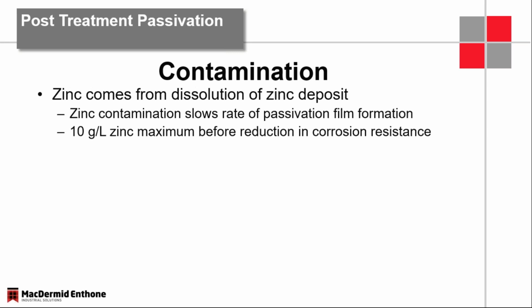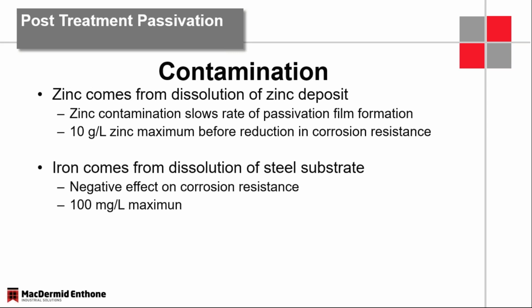Okay, so yes, we use 10 grams per liter as a maximum. There are Passivates, depending on how they're built. These Passivates are built with different organic acids. They're built with different sources of chrome nitrate or chrome sulfate. Depending on how they're built will depend on your upper limit for zinc contamination before corrosion resistance suffers. I use 10 grams per liter. At 5 grams per liter is when you should really start thinking about making a corrective action though. Whether it's a decant, whatever your corrective action would be.